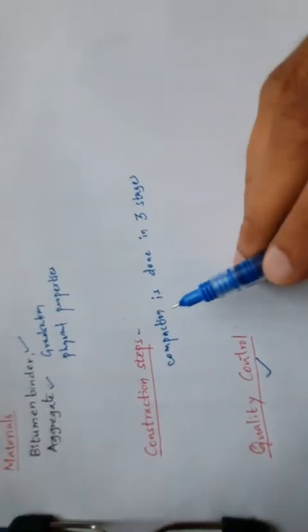And next, the construction steps remain the same here. The surface on which the first graded bituminous mix is to be laid is prepared by patching the potholes, sealing the cracks if you find any, and filling up the depressions. Then if the profile correction required exceeds 40 mm, the profile corrective course is to be laid separately using a mechanical paver and it is compacted.